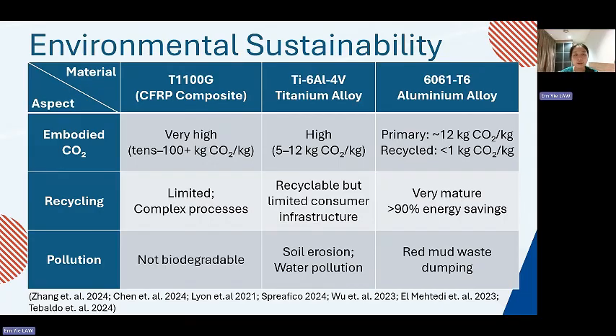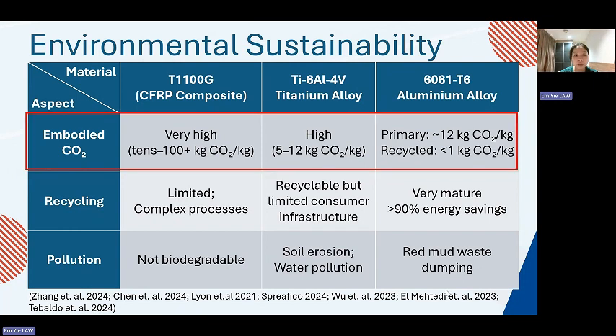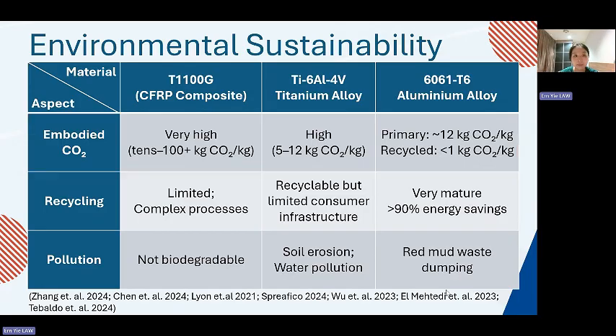Since our selected material is carbon fiber reinforced polymer, which is CFRP, we will discuss its long-term sustainability while comparing it with titanium alloy and aluminium alloy. CFRP offers excellent performance, but its environmental impact is significant. Its embodied carbon footprint is one of the highest among the three, ranging from tens to more than 100 kilograms of carbon dioxide per kilogram of material. This is far higher than titanium alloy, which is typically around 5 to 12 kilograms, and aluminium, which drops down to 1 kilogram if recycled.